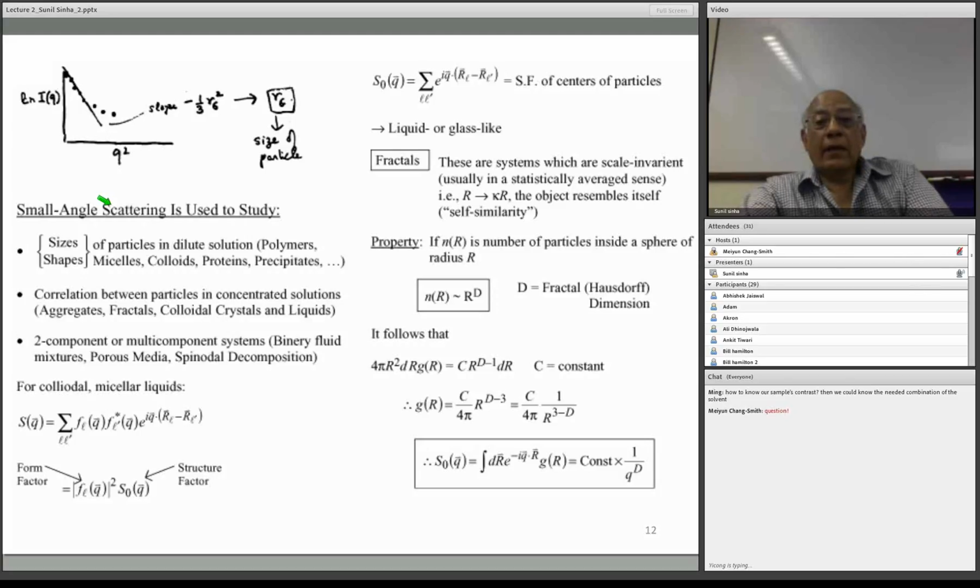But of course, in some cases, you don't quite know the sample, and then you have to do it by trial and error. There are very interesting small angle experiments, actually, where you slightly change the mixture of H2O and D2O, and keep measuring the scattering until you get a nice minimum in the curve where the contrast essentially goes to zero. And so you can contrast match by selectively and accurately deuterating partially your mixtures and doing this as a function of the concentration. It's a painful process, but it has been done several times, and it's often advised if you really want to very carefully get zero contrast for some part of your sample.